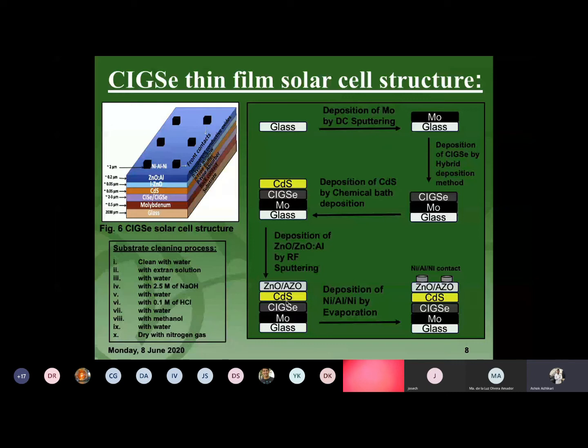After that, the glass is placed for deposition of molybdenum by DC sputtering, and then CIGSe by hybrid deposition method. Subsequently, CdS, zinc oxide, aluminum zinc oxide, and the front contact nickel, aluminum and nickel.